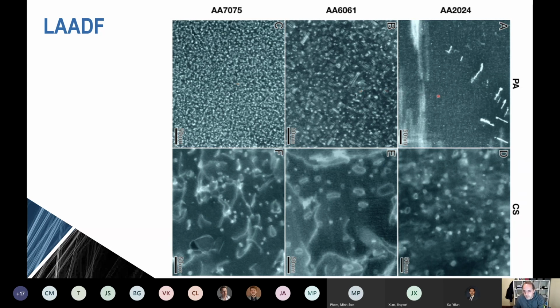And it's good to see them because you can see the length scale of the microstructure. The microstructures at the bottom are the microstructures of our cyclically strengthened materials. Now, it's important, these 2 microstructures have basically the same yield strength, but the microstructures are completely different. In the microstructures down the bottom, you can see dislocation loops, and these dislocation loops form as a result of the condensation of the vacancies that are generated by the cyclic plasticity.